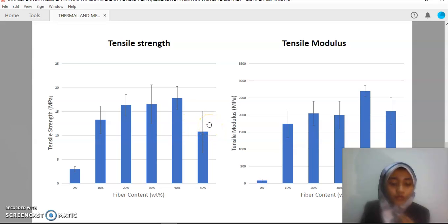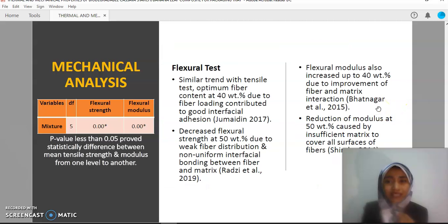It is due to higher fiber content, so the fiber is not adequately wetted by the starch, which caused agglomeration. We can see the agglomeration in the SEM results after this. For tensile modulus, it also shows the same trend, but slightly decreased at 30%, and then reduced at 50% fiber content due to structural changes in the starch arrangement when fiber was added. So the composite becomes less compact.